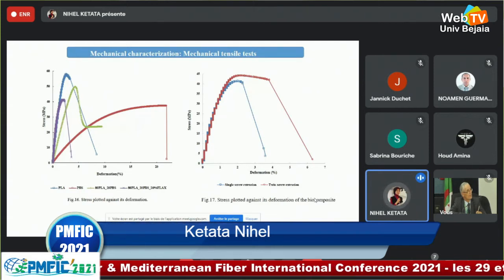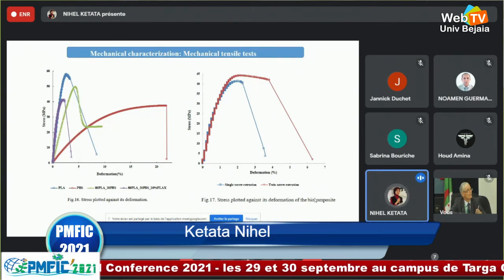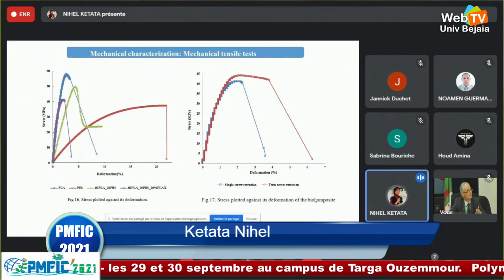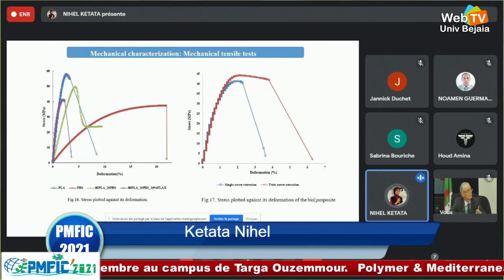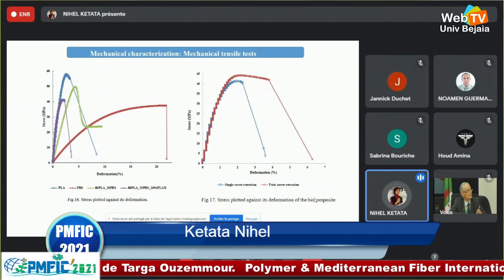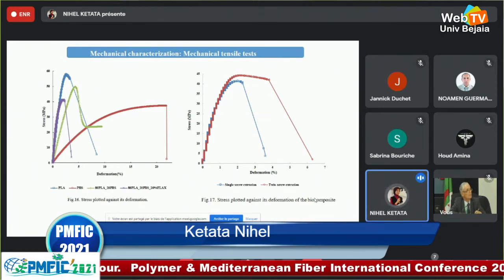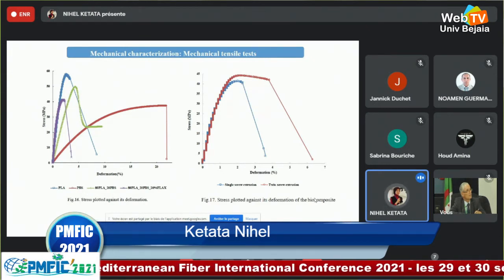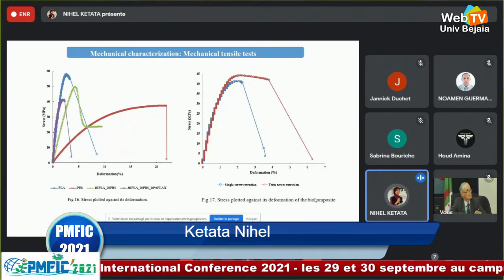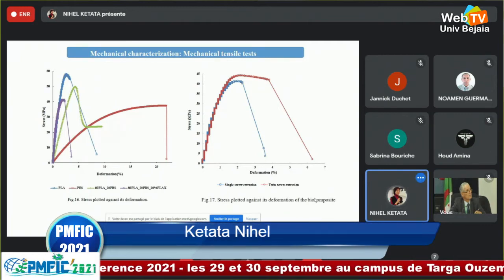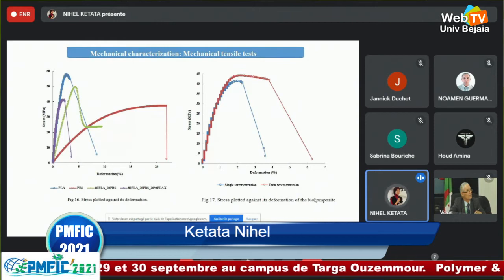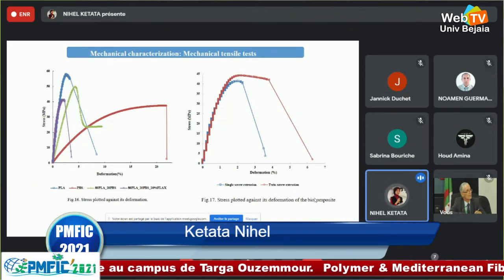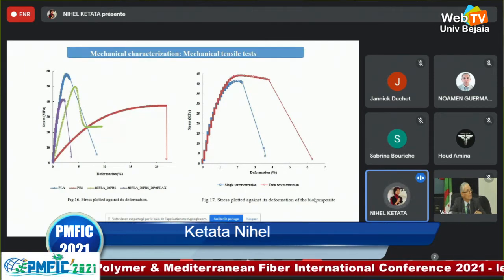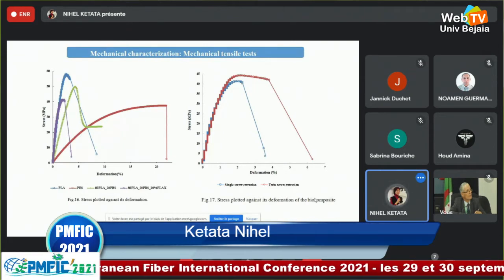The results also show that mixing PLA with PBS provides the desired stiffness of the material and gives us an acceptable modulus of elasticity, a good resistance, and elongation at break. PLA provides the desired rigidity of the material, and PBS is responsible for the elongation, reflecting the fact that PLA and PBS are compatible. Finally, the addition of flax fiber leads to an improvement in properties such as the tensile modulus. On the other hand, we observe a decrease in deformation and therefore in the elongation at break.